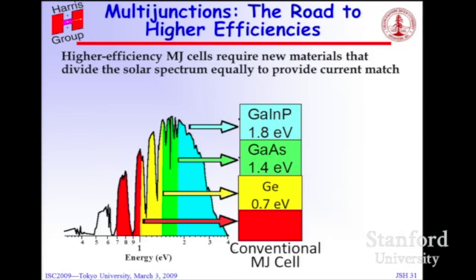This is a slide from our own Jim Harris, who has been making these cells, I think, for more than 20 years, although not continuously. And the idea is simple. You have high band gap, medium band gap, and low band gap cells. The light needs to go through the high gap cell first. You harvest the high energy photons, and that cell can generate a high voltage. And then the medium band gap cell grabs the middle of the spectrum and gives us an intermediate voltage. And the low gap cell takes most of what's left. And this works. It works great.